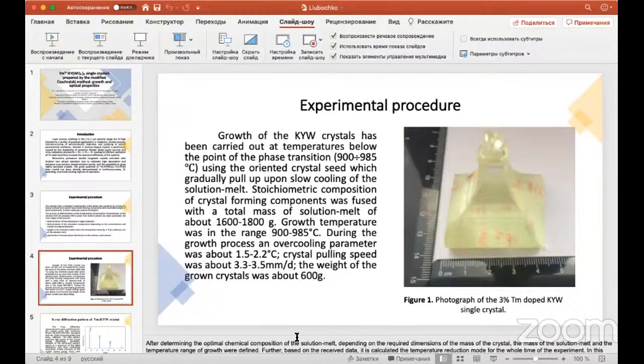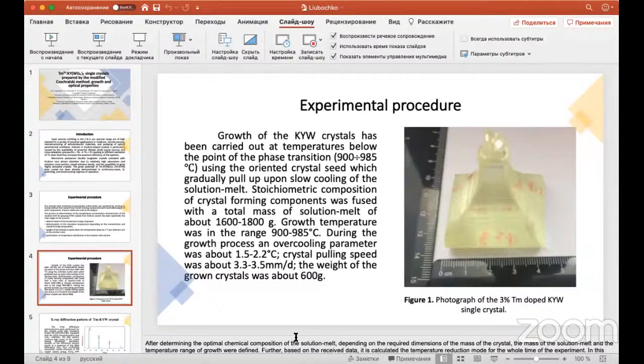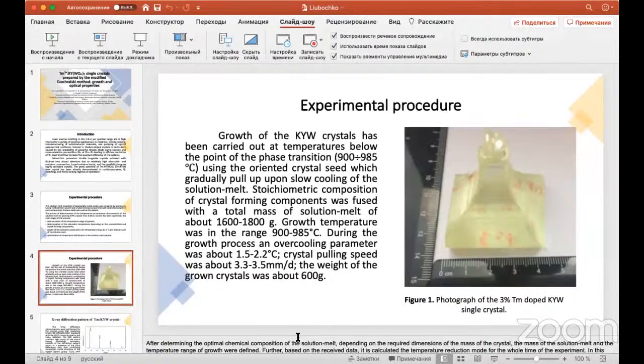600 grams. After determining the optimal chemical composition of the solution melt depending on the required dimension and mass of the crystal, the mass of the solution melt and the temperature range of growth were defined. Further, based on the received data, the temperature reduction mode is calculated for the whole time of the experiment.